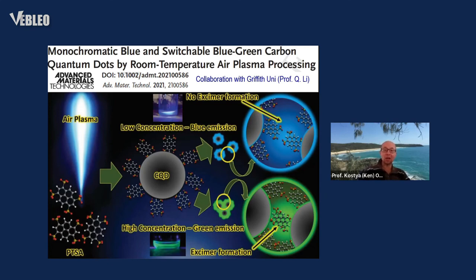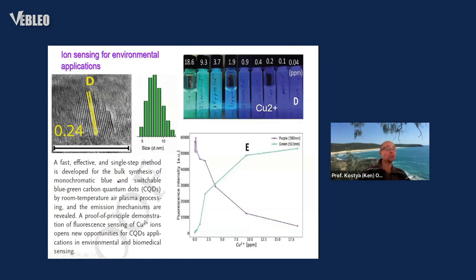And in that way, they can change color. Very interestingly, when we applied those particles for testing copper 2+ contaminant in water, then depending on the concentration of this contaminant, the carbon dots displayed different colors of optical emission, so that you can see along all these tubes different concentrations of Cu2+. As the concentration increases, the color also changes from blue to green. And this is another application of how plasma processing can be used to produce active functional nanomaterials for detection of